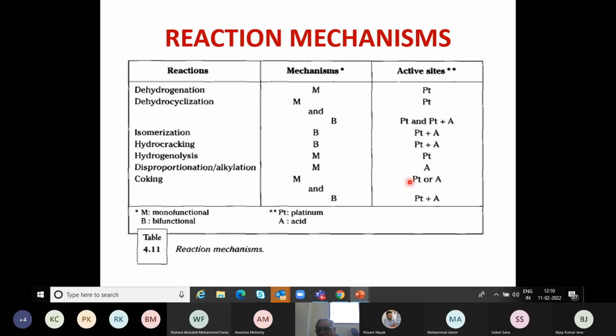This slide is a very important slide, which tells you the role of these two sites which we talked about. It's a good summary of what we talked about. For example, the dehydrogenation reaction. M stands for monofunctional. It is dehydrogenation, just monofunctional, and it just needs the platinum as an active site for doing the reaction. The dehydrocyclization needs both M and B. That means bifunctional, where it needs platinum as well as the acidic site.